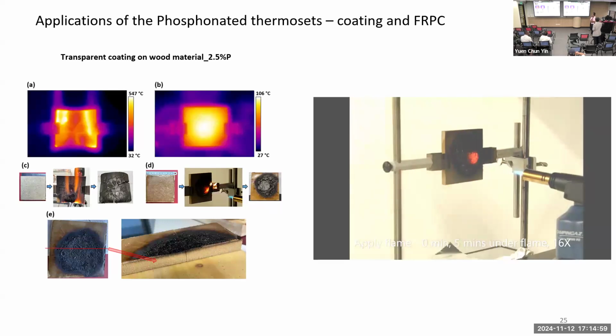And what's the thickness of your coating on wood? Oh, 500 micron. Yeah, 0.5 mm. Okay, quite thin. So the result is quite good. Does it give intumescent, not obvious? Yes. Well, you can see the intumescent here. What they did was they took it off. We forgot to take a picture of the horizontal cross section, I would say. But you can see this one here, giving an idea of the mushroom.